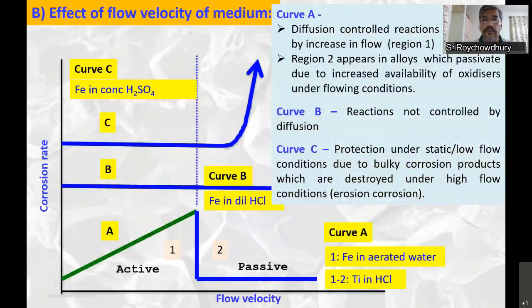Let's see the effect of flow velocity. Again, there are different possibilities. Like curve A, there's a linear increase in the corrosion rate, and then a sudden fall, and a low corrosion rate is maintained. As you can understand, this is mainly due to the active-passive transition. So what does flow have to do with it? If there are any diffusion-controlled reactions, it means the oxidizing species has to reach the surface in order to form this passive film.